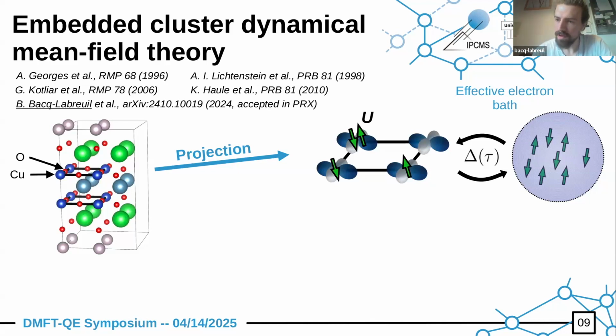And integrating out all the rest of the degrees of freedom, it can be cast into an effective electron bath with which the impurity can exchange electrons dynamically. And the only difference with when you apply DMFT on the Hubbard model is that here, basically, we project all the degrees of freedom of the crystal, right? So the electron bath contains all the other degrees of freedom of the system. So not only the other copper dx minus y squared orbital, but all the others, everything that lies there.